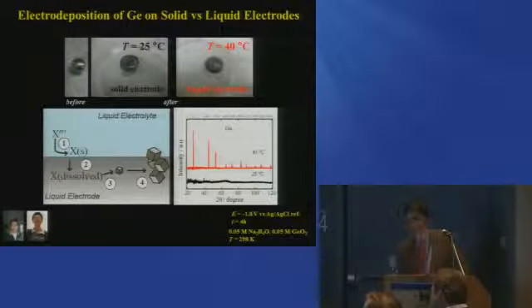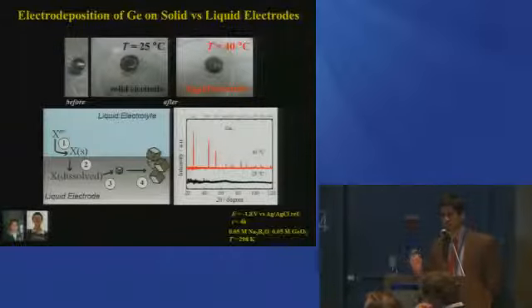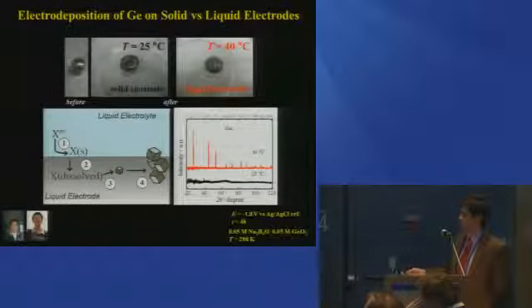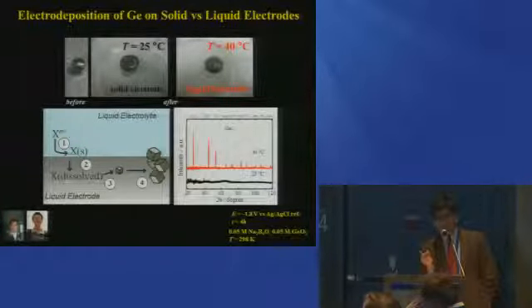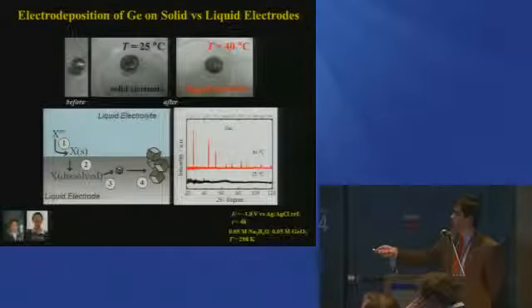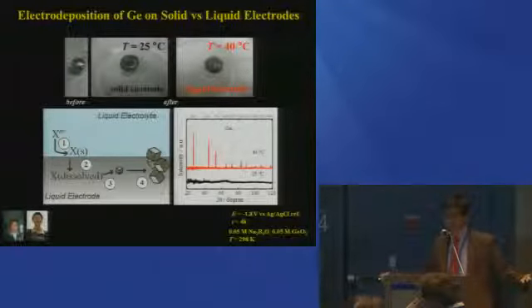The net effect is that you can do a cool experiment with gallium that you couldn't do with mercury. Mercury freezes at a relatively low temperature, but gallium freezes right around room temperature. So you can do an electrodeposition where you're just above room temperature, at 40 degrees, using liquid gallium, or just under room temperature with a solid piece of gallium. If this process works, then with a liquid you have access to this pathway, and when it's a solid, you don't. And so you shouldn't get crystalline germanium.